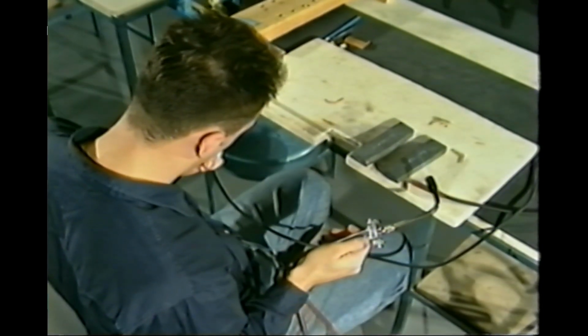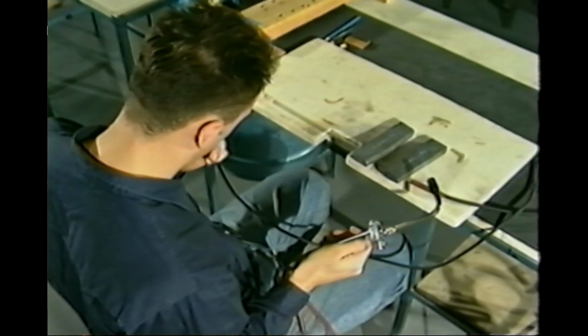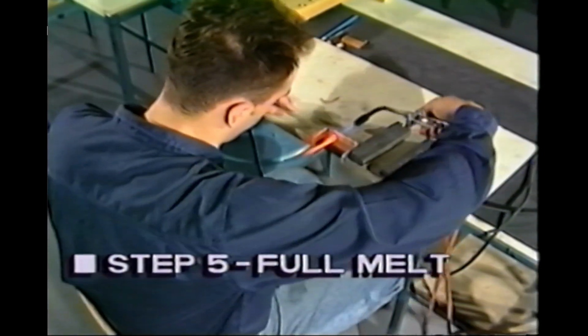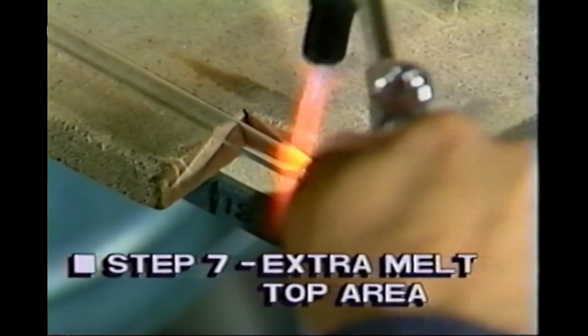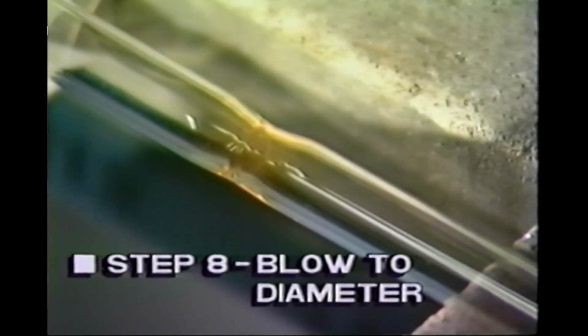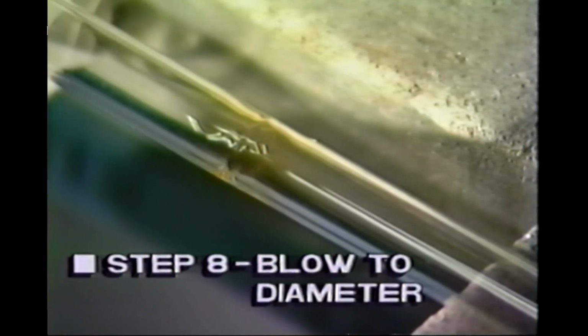Remove the flame and blow gently into the blow tube until the tube diameter at the melting point is restored evenly around the tube. After this melt and blow operation, many of the ridges and folds in the joint will have been melted away. At the end of this repeat melt and blow, all of the ridges and folds should have been melted away. If this is not the case, a further melt and blow will be necessary.